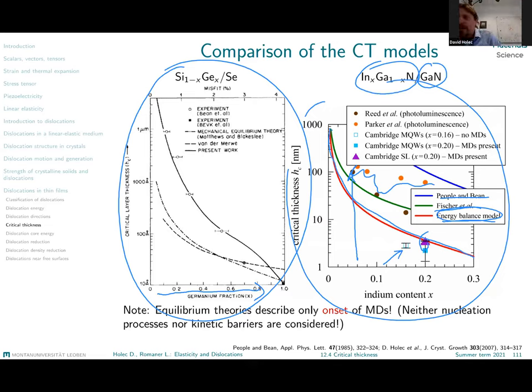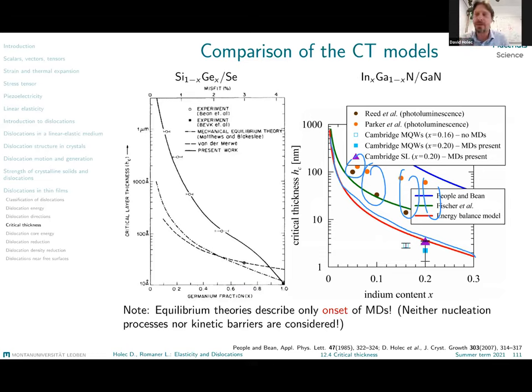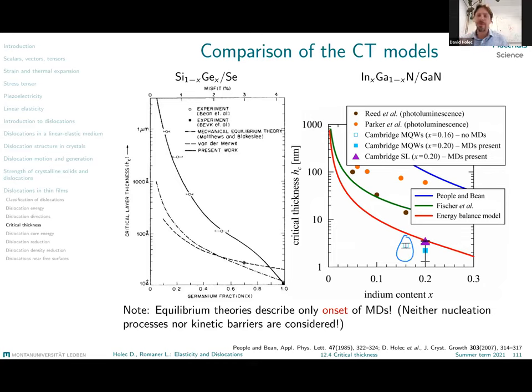The energy balance model — balancing the misfit strain energy with the dislocation energy — is the red curve shown here. The data points indicate whether, for a given composition of thin film — in this particular case indium gallium nitride grown on top of gallium nitride — misfit dislocations were observed (filled symbols) or whether they were not observed. A couple of comments: firstly, dislocations are observed when we are above the critical thickness line — good. Secondly, they were not observed below the critical thickness — again, good.